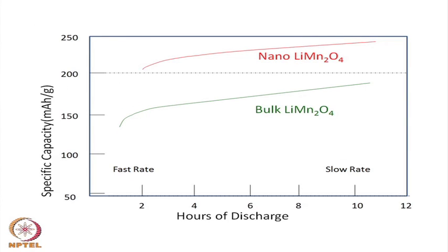The nano effect is there in this material, in fact it is very important. One of the major research areas is whether the materials can be used in nano powder form, and what effect that has. Here, in the case of a particular spinel type compound, LiMn2O4, if you prepare it in micro fine powders versus nano fine powders, you can see a significant increase in the specific capacity.